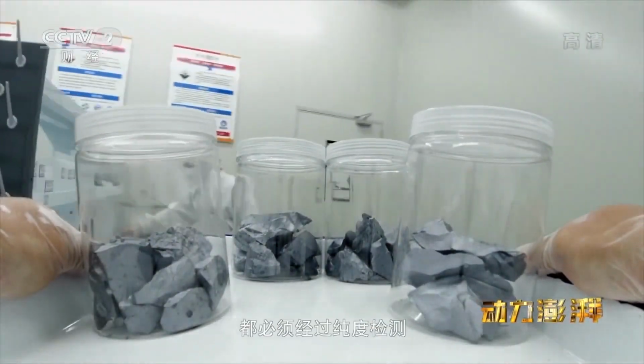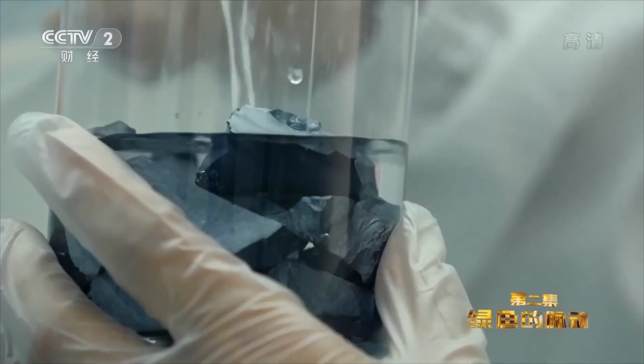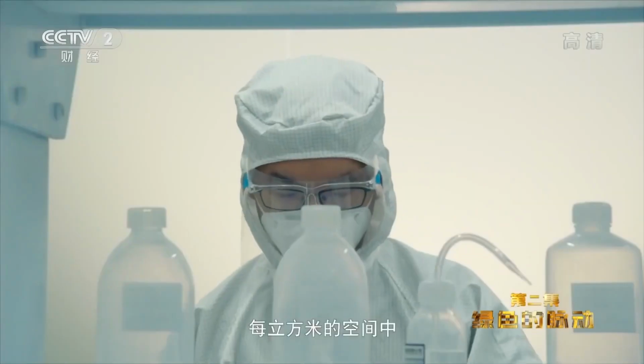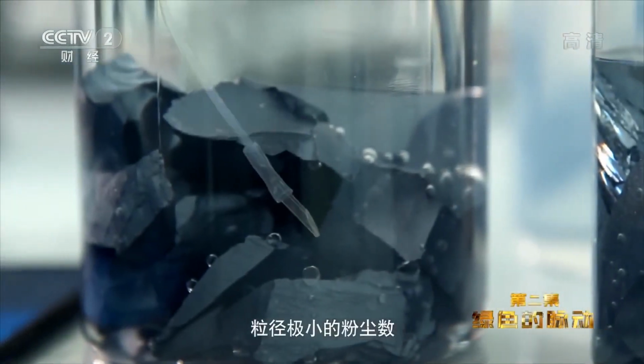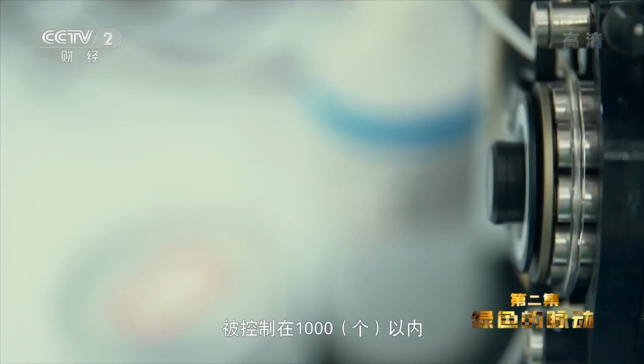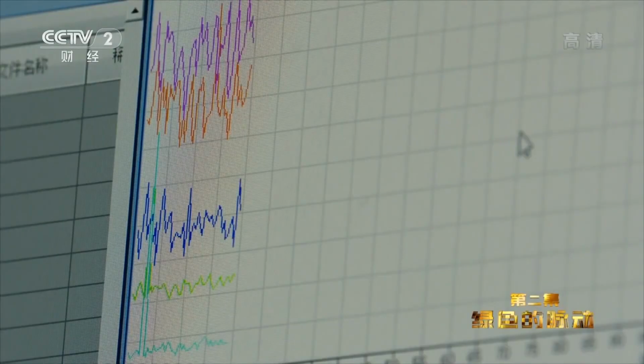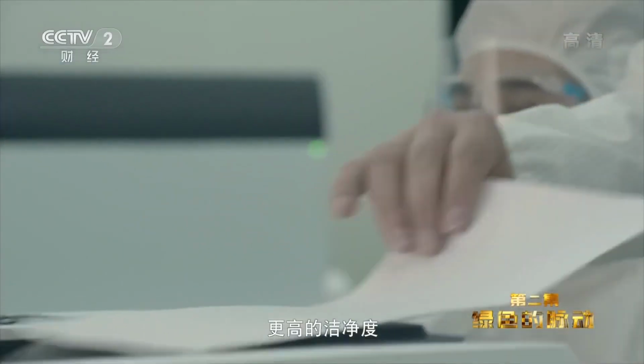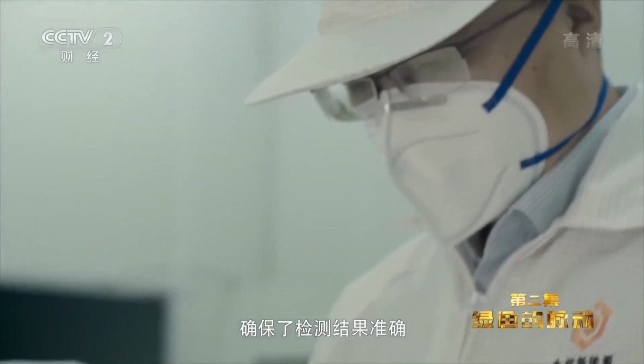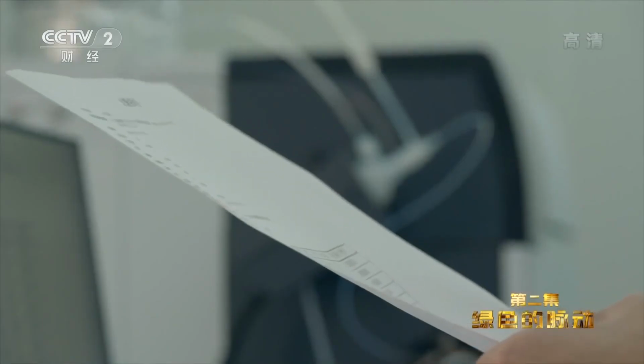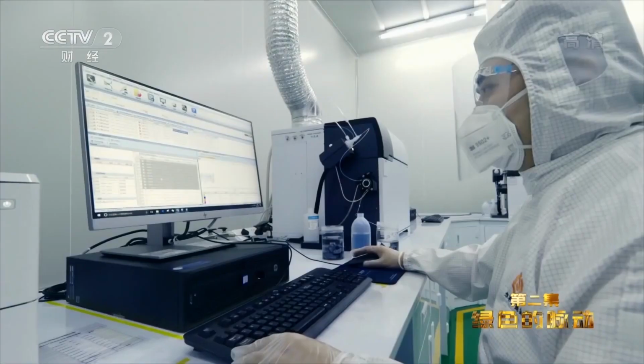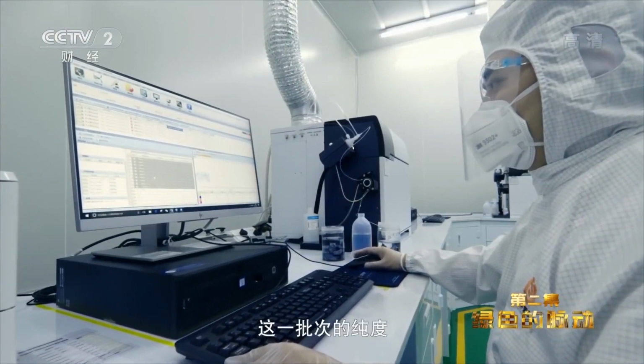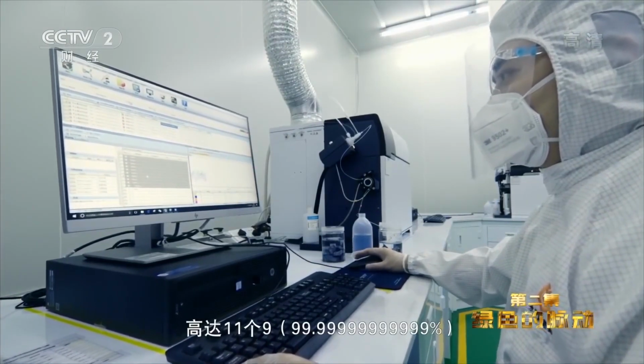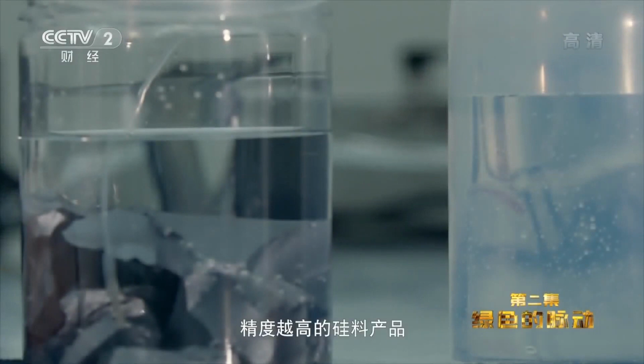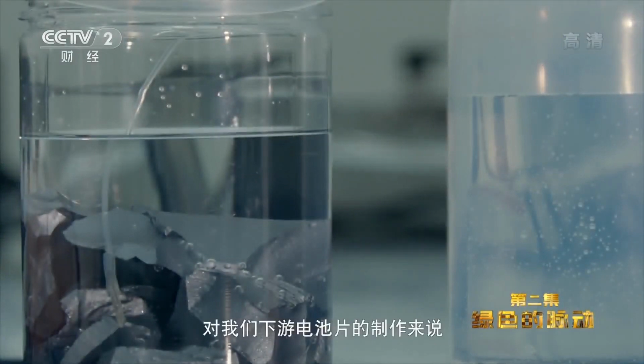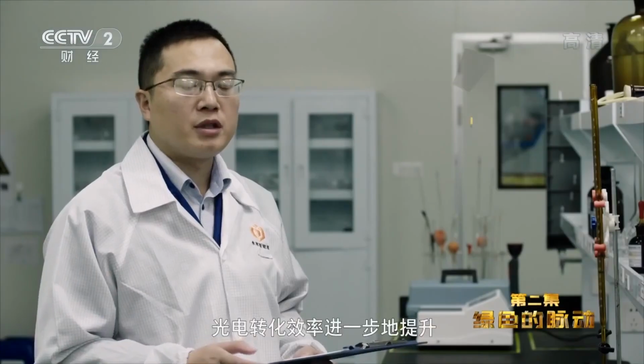The silicon rods from each furnace must be tested for purity. In the testing center, the number of dust with extremely small particle size is controlled within 1,000 particles per cubic meter. Higher cleanliness ensures accurate test results. Well, this batch is of good quality. The purity of this batch is as high as 11 nines. The higher the purity of the silicon material, the higher the photoelectric conversion efficiency of the cell.